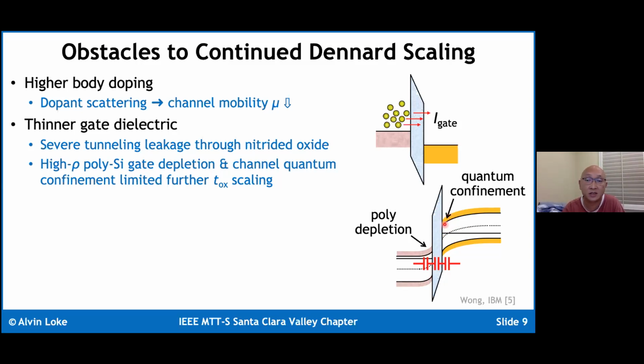Okay. The net result is, because of the quantization of energy levels, as well as restrictions due to density of states, restricting the number of electrons you can populate at these lower level quantum states, electrons cannot be infinitesimally close to the silicon surface side of the gate oxide, which means that the charge gets pushed out further away from the interface. So the net result is you essentially can think of charge on the gate being physically separated from charge in the channel by essentially three capacitors in series, which obviously is a lot less than the capacitance of one device of just the gate oxide itself. Okay, and so you have less gate control.